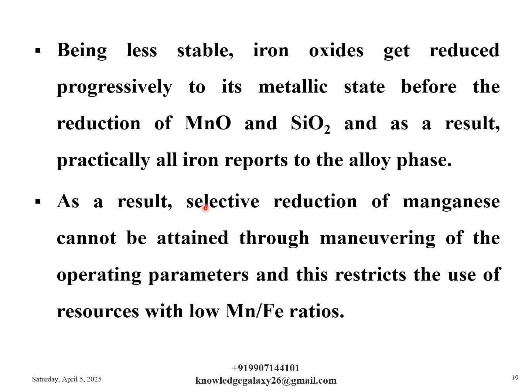As a result, selective reduction of manganese cannot be attained through maneuvering of the operating parameters, and this restricts the use of resources with low Mn by Fe ratios.